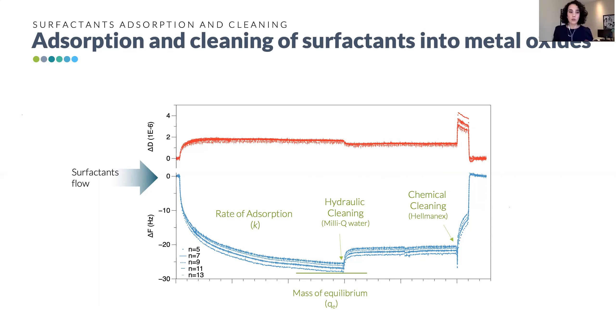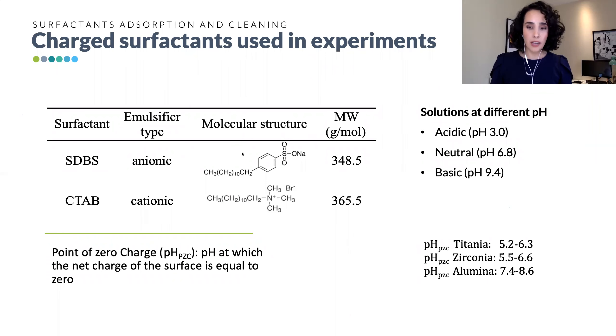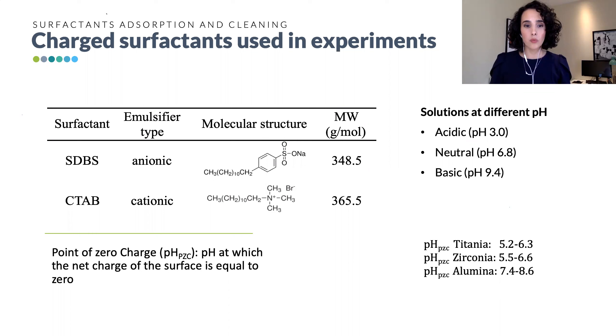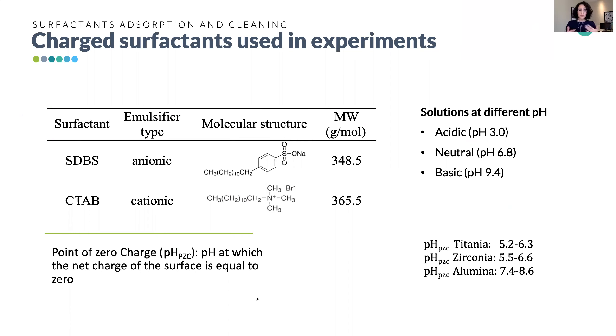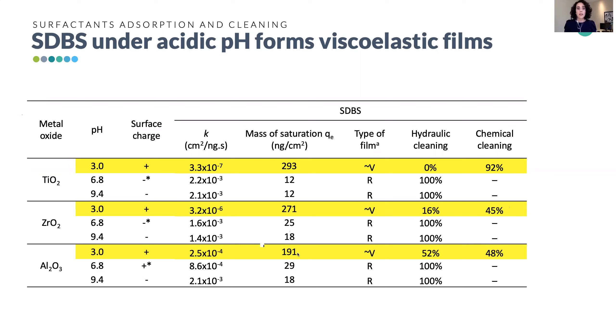We initially used charged surfactants: anionic SDBS with a negative head and cationic CTAB with a positive head. We prepared solutions at different pH values — above and below the point of zero charge of the metal oxides. The point of zero charge is the pH at which the net charge of the surface is zero. For SDBS, we found that under acidic conditions the adsorption rates were lower compared to other pH conditions, but the mass adsorbed was the highest under acidic conditions. At first sight this might be attributed to electrostatic interactions between negatively charged SDBS and positively charged metal oxides.